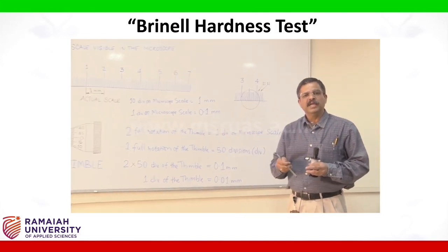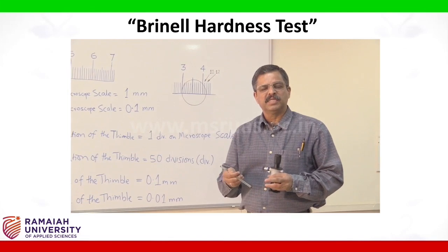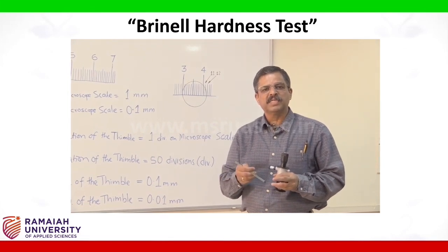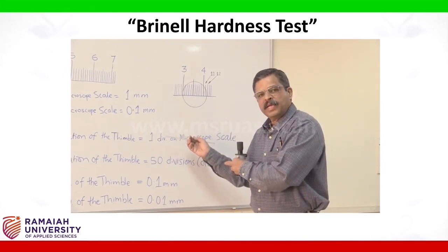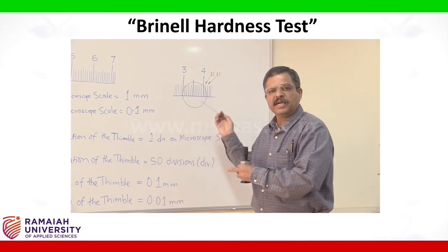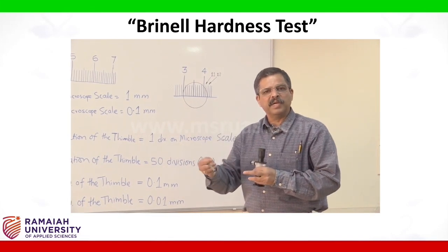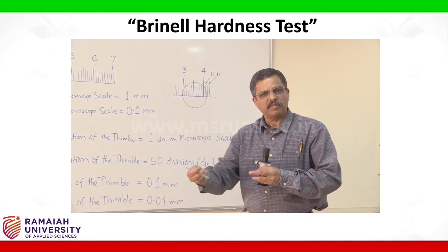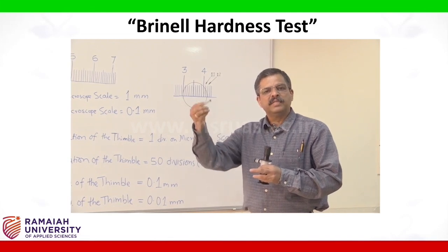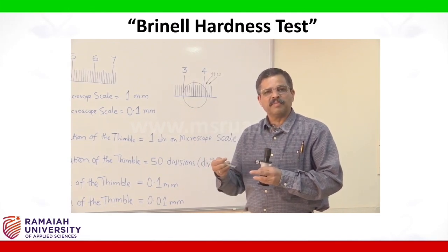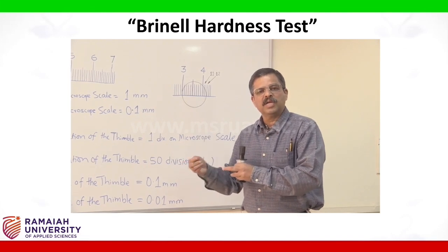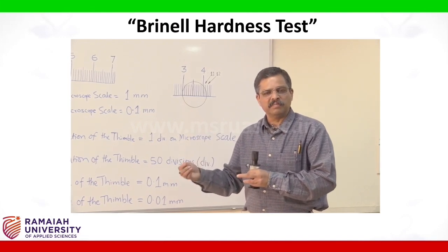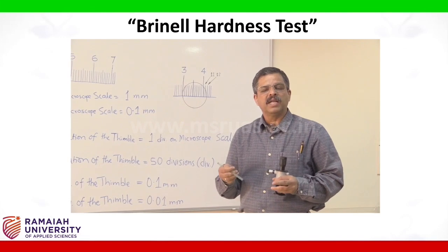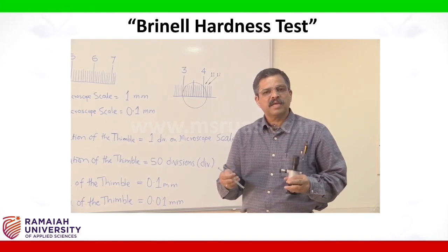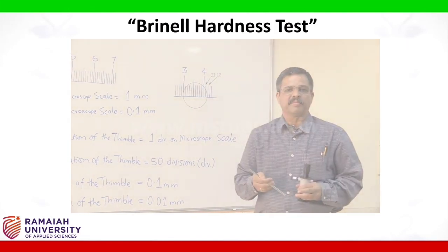Similarly, you have to conduct 3 experiments at various positions in the workpiece and follow the same procedure by measuring the indentation, finding the diameter, and later applying the formula again, and you will get 3 Brinell hardness numbers. Find the average of these numbers to get the final Brinell hardness number, which is the Brinell hardness number of the material. This completes the experiment.